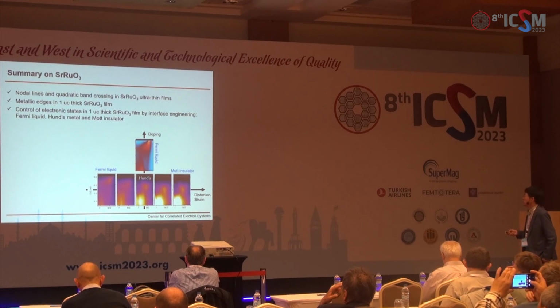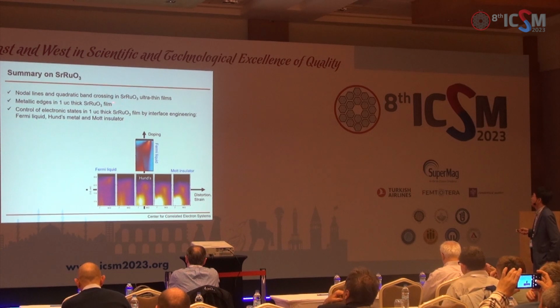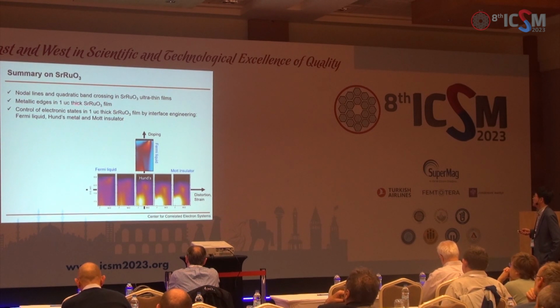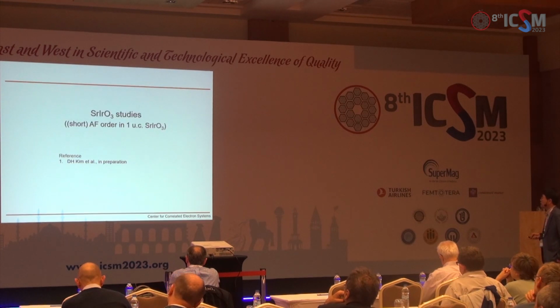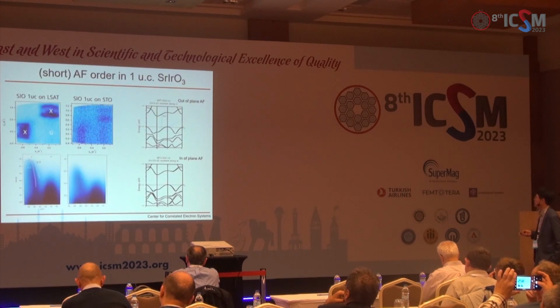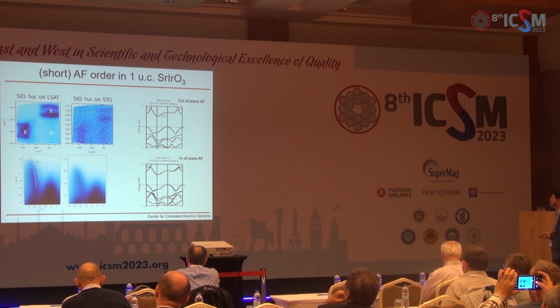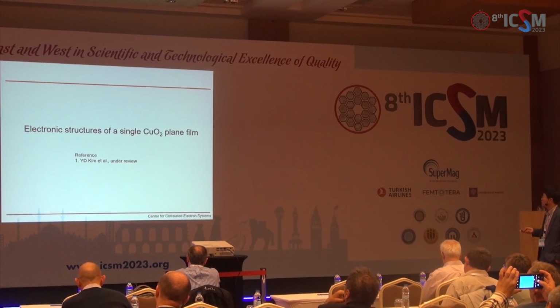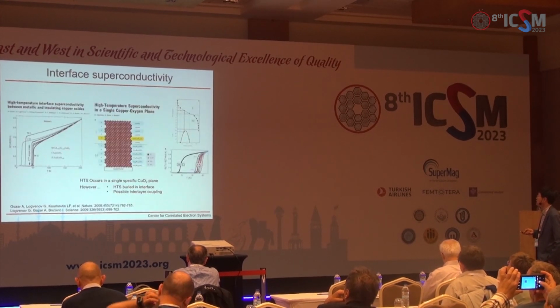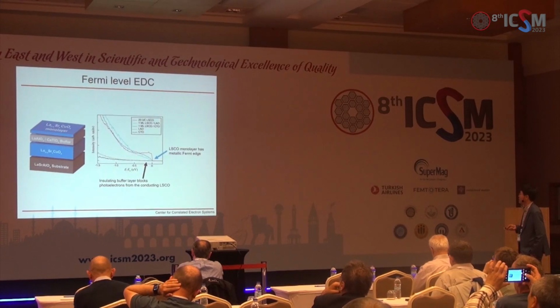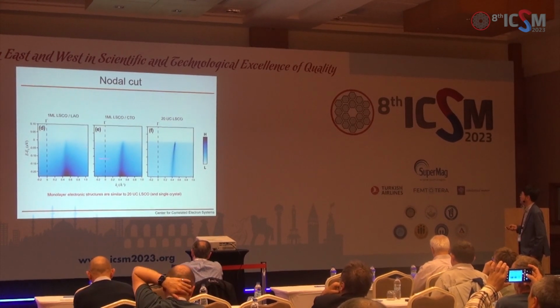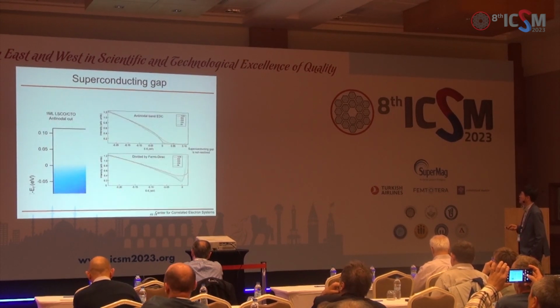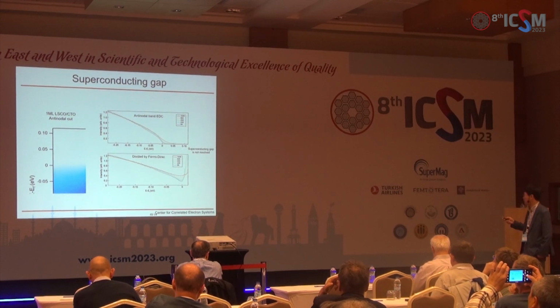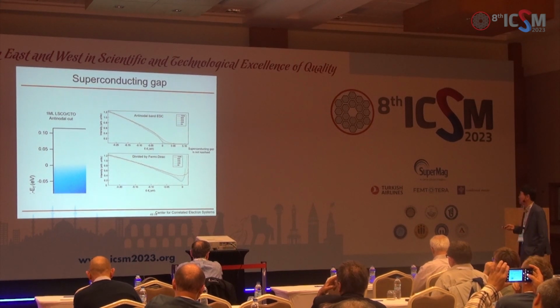So, if I were to summarize our work on strontium ruthenate, I talked about nodal lines, metallic edges, and we control metallicity of this one unit cell strontium ruthenate. We have other works on strontium iridate. We see signature of antiferromagnetic order, even down to one unit cell of strontium iridate. And though I'm not going to talk about it, we are also trying to grow single unit cell of lanthanum strontium copper oxide, and we were able to measure band structures, even though at this moment we weren't able to make it superconducting. We have a single unit cell copper oxide plane material with the electron structure.